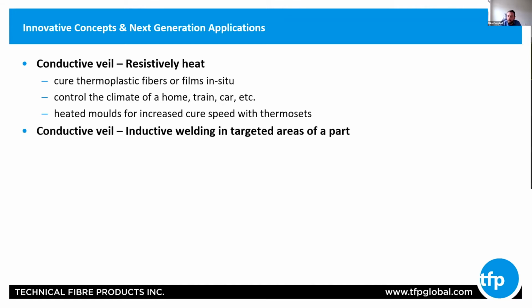Inductive welding with conductive veils. By placing the metal coated veil in very specific areas of your composite layout and applying a magnetic field, you could target areas to cure.